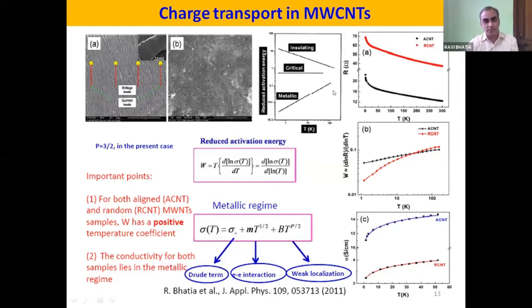So just by comparing the result with this particular graph, one can easily say the sample conductivity lies in the metallic regime, where the two important terms are occurring, the electron-electron interaction and weak localization. However, we need not go into these details. The important message here is that the VRH conduction, which is the exponential decay of conductivity with temperature, is not observed in this sample. One can ask a question, why so?